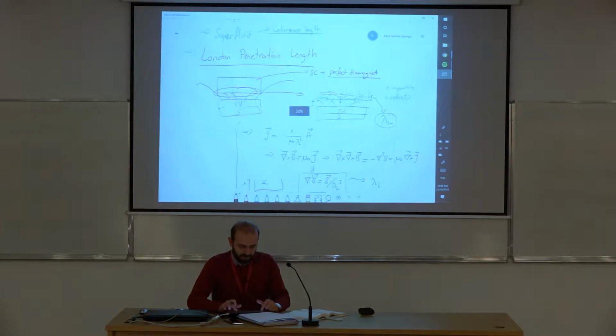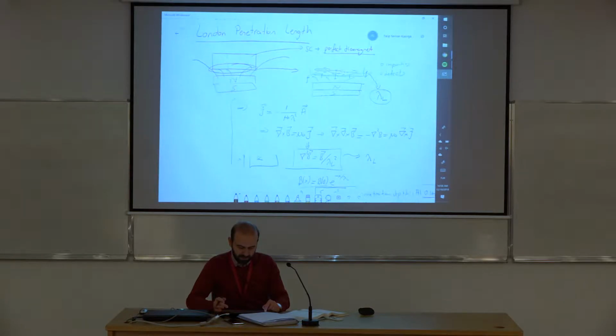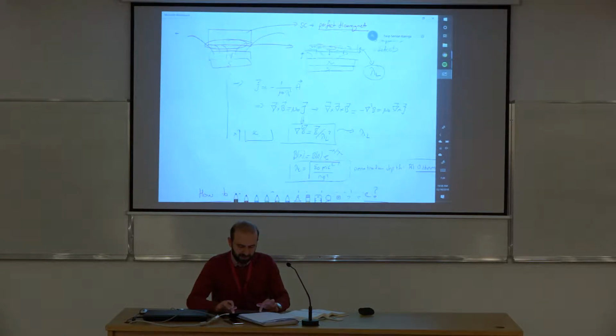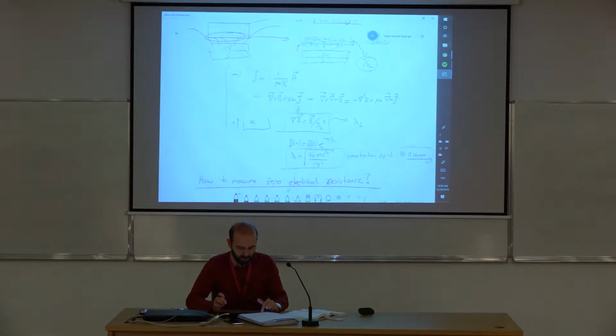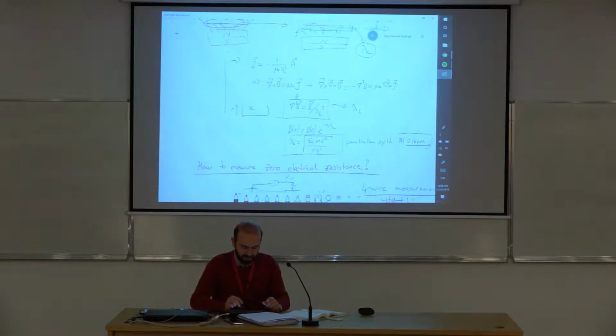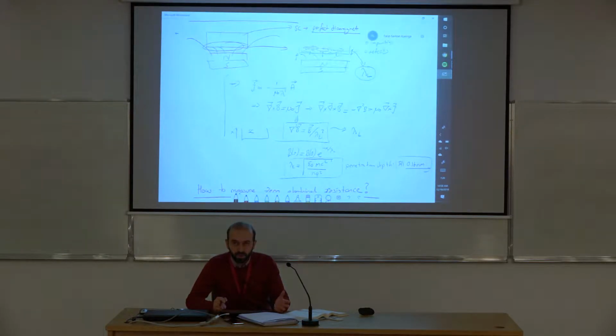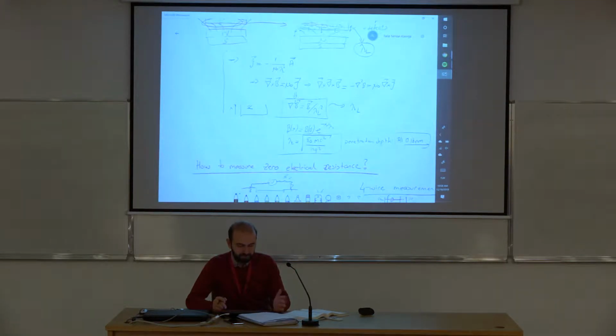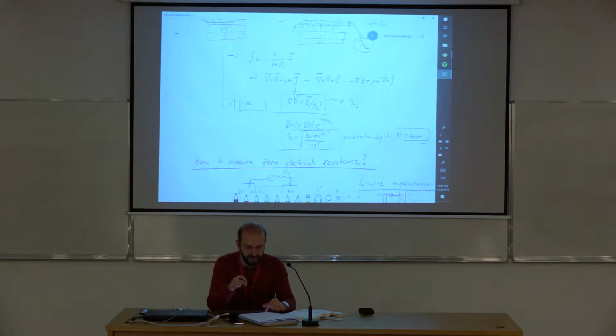Then we discussed the London penetration length, which is a length that shows how deep a magnetic field can penetrate into a superconductor, and it is given by such an expression. For the case of aluminum, it was only about 16 nanometers, which is extremely shallow. But this penetration plays an important role in some of the unique features that we observe in superconducting materials, like magnetic levitation. So when you place a magnet over a superconductor, or it can be the opposite, you can place a superconductor over a magnet.